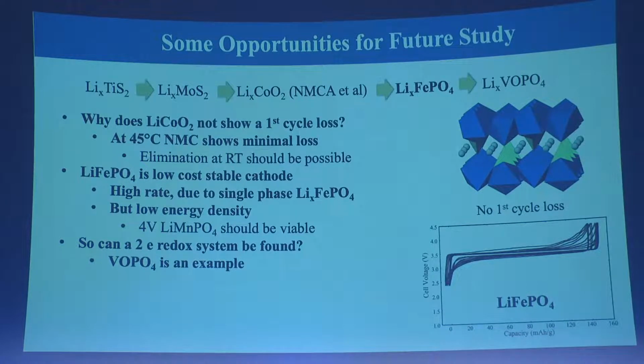But the issue here, this is what we call a two-phase reaction. So you've got iron phosphate, lithium iron phosphate, and if you all know your phase rule, that means you've got two phases all the way, a single voltage all the way. So how do you tell whether it's 20% empty or 80% empty? Read Tesla's manual, because they're putting this in some of the Model 3s these days, and it says whenever you get home, plug them in. So it's always at 100%. So there's in fact no easy way, unless you have a coulometer that actually measures how much you're taking out.